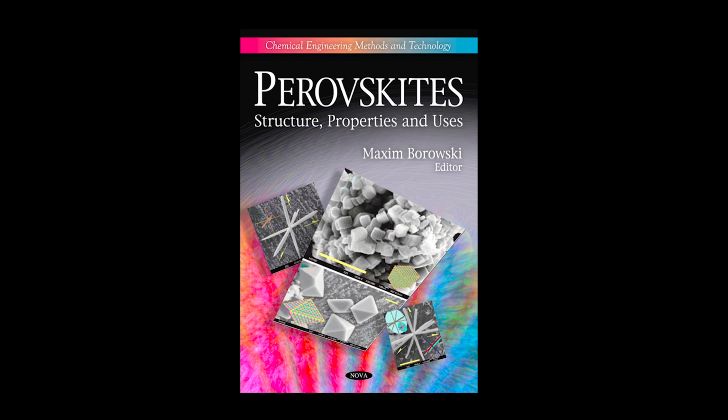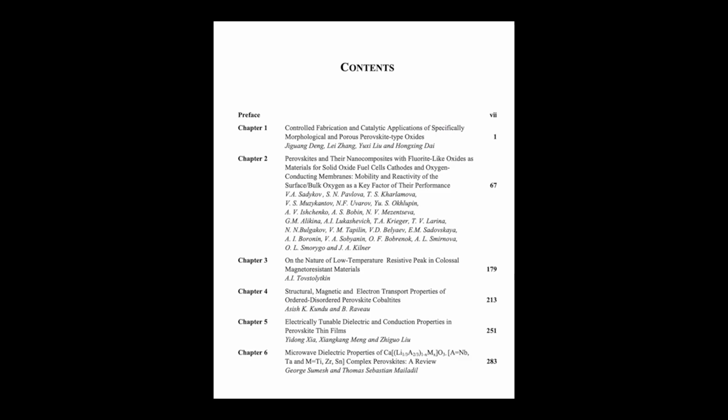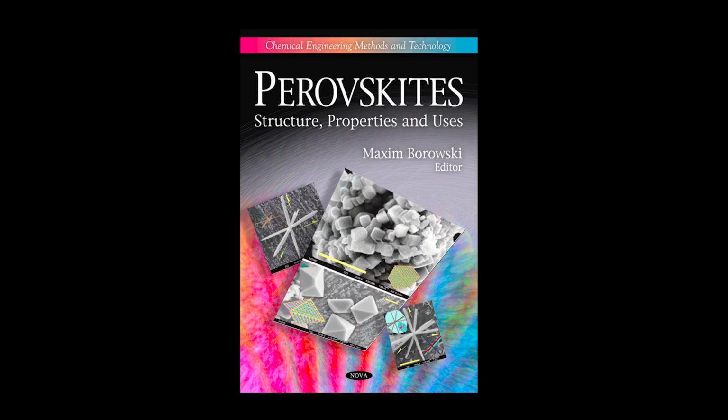If we substitute some divalent strontium, Sr2+, onto the A site in place of the trivalent lanthanum, La3+, we achieve two beneficial things simultaneously. First, to maintain charge neutrality, the substitution promotes the formation of more oxygen vacancies, which we just said are needed for reaction sites. Second, the substitution forces some of the manganese on the B site to increase its oxidation state, promoting the formation of the highly active Mn4+ species alongside Mn3+. This A site doping enhances both the electronic conductivity, which helps the redox cycle, and increases the number of active surface sites, vacancies, and higher oxidation state B cations, often dramatically boosting the overall catalytic activity.